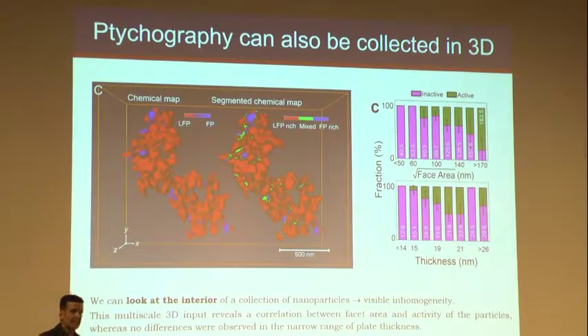Okay, so like I said, like everything that you can do with an X-ray microscope, if you can rotate your sample stage, you can do it in 3D. These are the same small particles that I was just discussing, but now there's many more of them, and this was done tomographically. We rotated the sample stage and we reconstructed the object while maintaining the chemical contrast. And so this is still at around, I believe this was determined to be 11 nanometer resolution based on some analysis of the images. And now you're able to look at the inside of the objects with this very high spatial resolution.